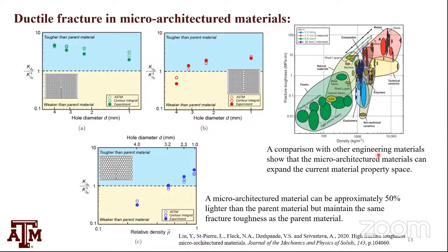Now, when we plot a simple Ashby map, here are the lines that represent our lattice, our microarchitecture material. And you can have a material which has a density less than that of water, that's 1000 kg per meter cube, and a fracture toughness greater than 10 megapascal root meter. That was pretty neat in this case.